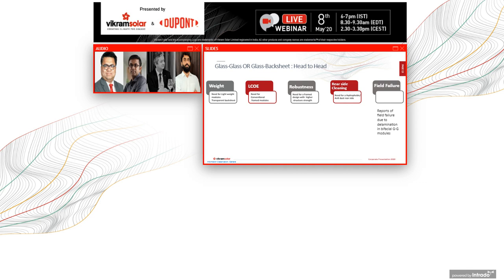When the module is installed and under severe thermocycling and humidity conditions in the field, these compressive stresses get released and the module shatters. This has been one of the major failure modes of glass modules, and therefore it's a significant reliability risk for these kinds of bifacial modules being installed in the field. Hence, there's a need for a field-failure-proof bifacial module. And that is where the transparent backsheet glass bifacial module comes in.